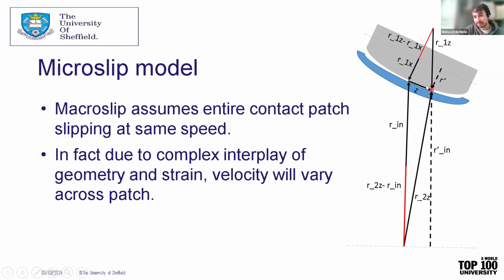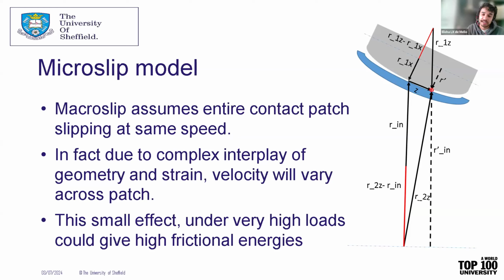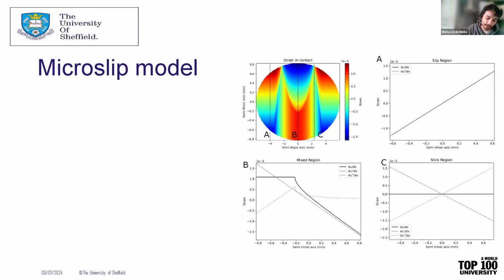There are effectively different radii due to curvature and this tilt. And this means that when this roller rotates, different points along the surface are going to be moving at different speeds. So there's quite a complex interplay of things going on, and there's also effects due to strain, so elastic deformation of material due to high loads, and this needs to be fully considered to properly understand what's going on. Because of this, even very, very small differences in speed across this contact surface, we get a very small slip, and because the system is so highly loaded, we could potentially get very high frictional energies. So that's what my model went on to investigate.